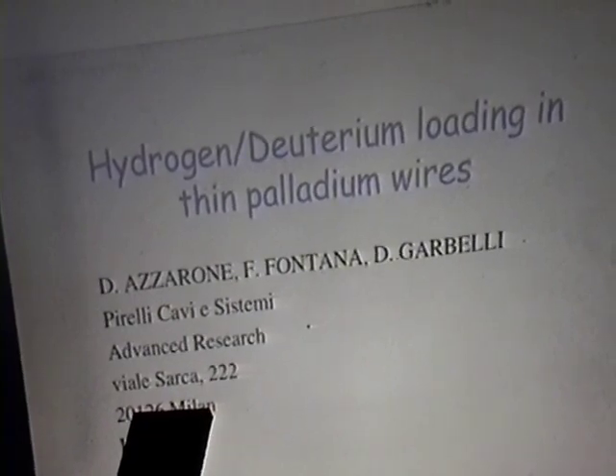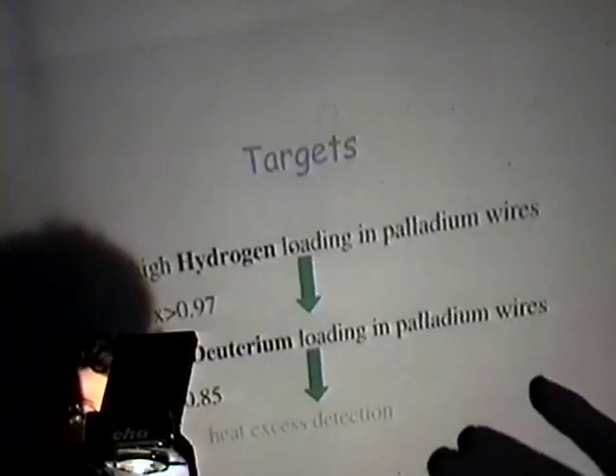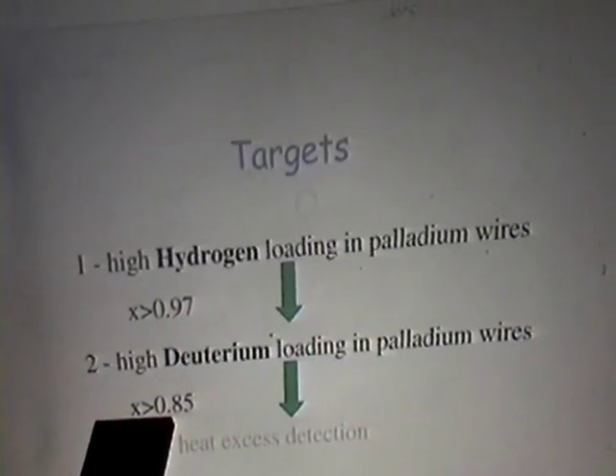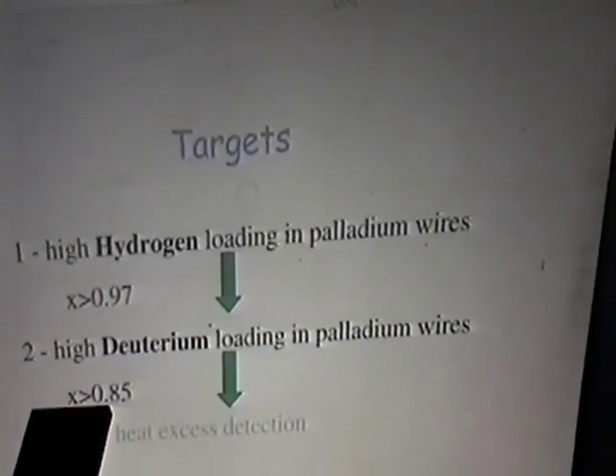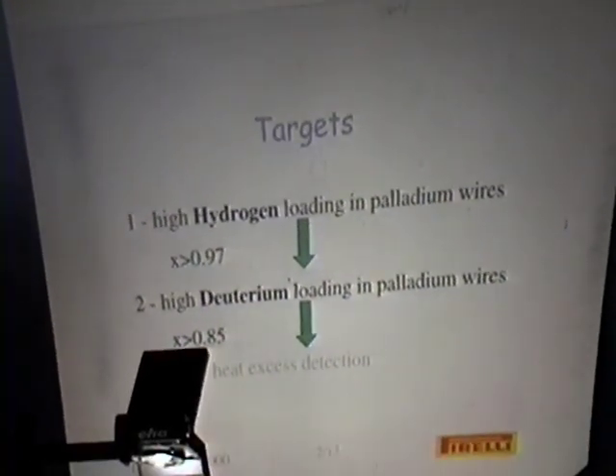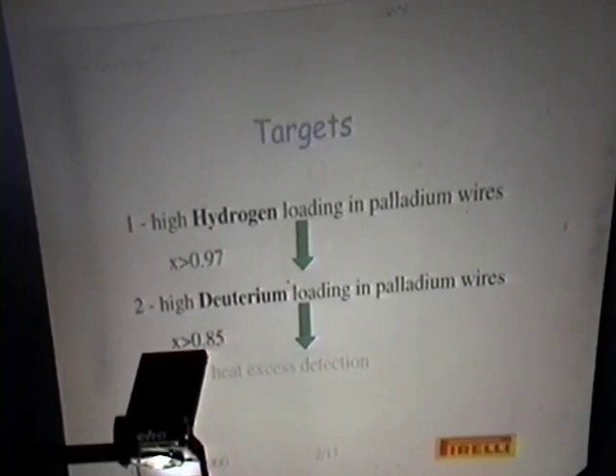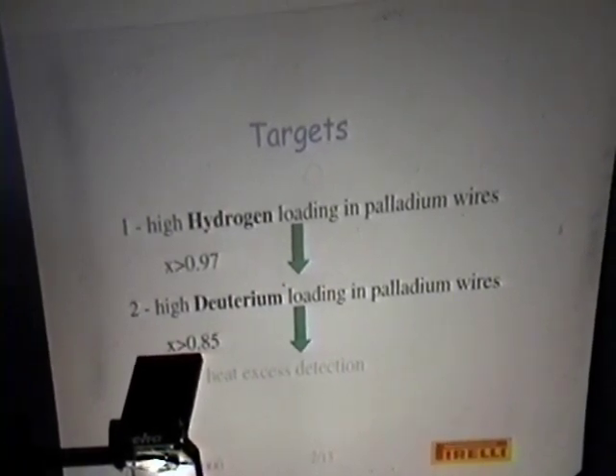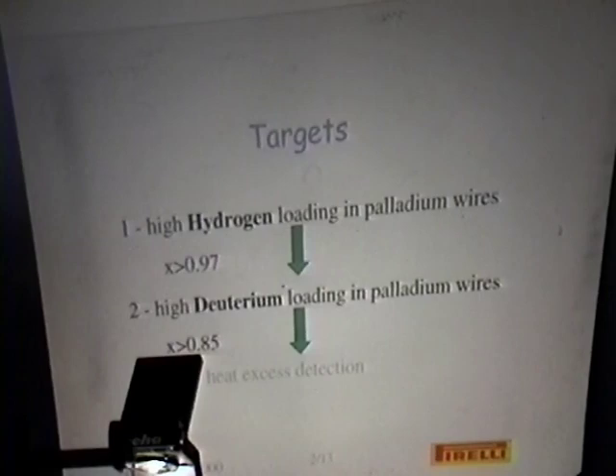With hydrogen and deuterium. The objective, the targets of our job were to load the hydrogen in thin palladium wires up to, I indicate here, 0.97, because we use the Baranowski curve to measure the loading, and this is the limit of that curve.